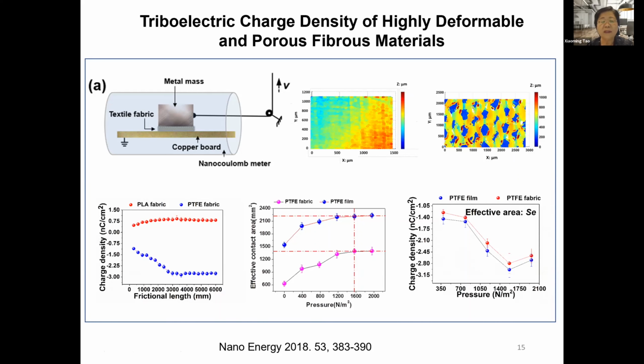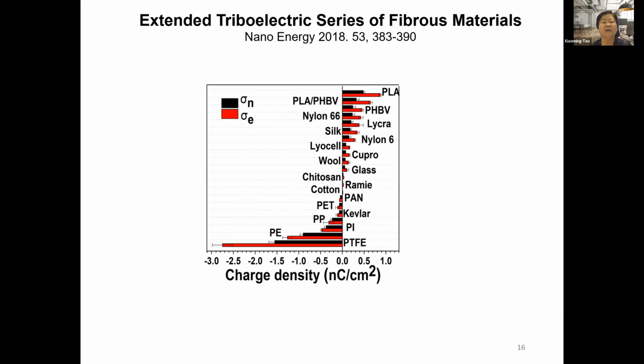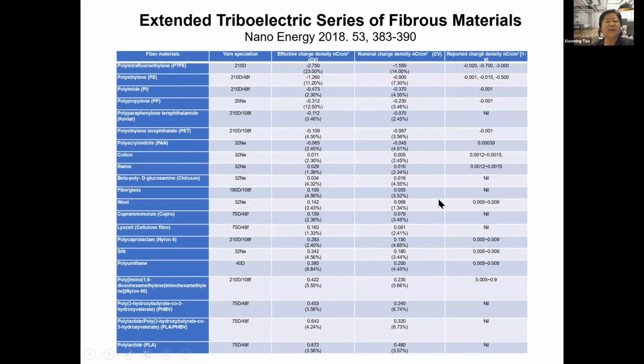And then we need to find out, in this fabric, which one is the best one. We look at quite a lot of new fibers coming into play, and we construct a new extended triboelectric series table from our experiments. Now, here I have two charge densities. One is red, the other is black. The red one is the actual charge density after densification under certain pressure. The nominal one is not stable, because the contact area is small, and when you change the pressure, that value increases. Normally, it's about half of the densified one. Based on this, we have the new table with all the charge densities.